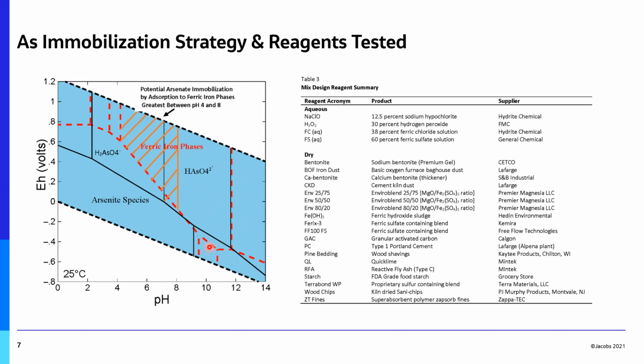And in fact, I will show you mix designs where we started with an initial TCLP of 40, and because we didn't get our pH right and we were strongly alkaline, we in fact doubled up to 80, which is, no bueno. So in terms of looking at reagents that we're going to be able to dewater a highly liquid material and to have combinations with iron and also sulfur, which is known to immobilize arsenic, we looked at probably 30 to 40 reagents.